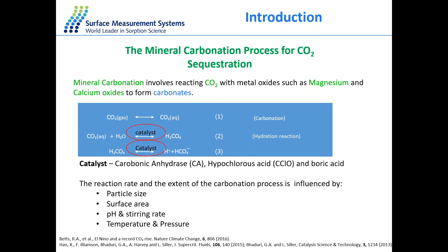The aim of this work is to replace these catalysts using nickel nanowires or nickel nanoparticle catalysts. The reaction rate or extent of the carbonation process is influenced mainly by particle size, surface area, pH, stirring rate, and temperature and pressure. The main goal of this work is to study nickel nanowires and nickel nanoparticles in silica aerogel catalysts and compare their performance for the carbon dioxide hydration reaction.